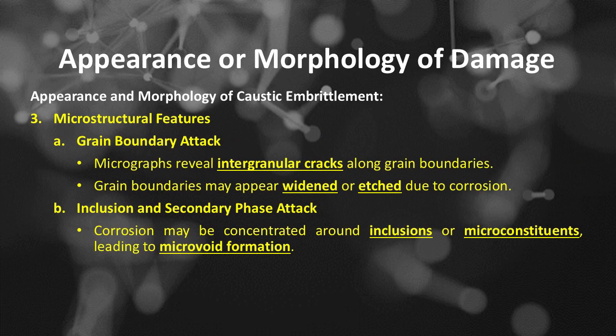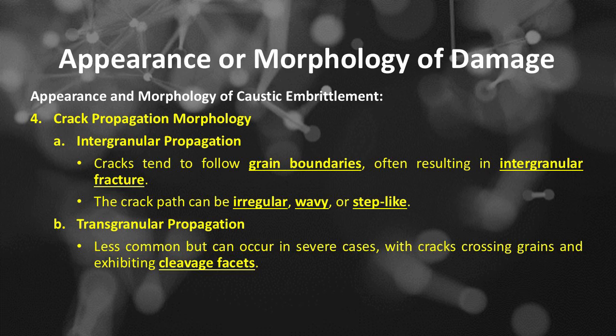Appearance and morphology of caustic embrittlement. Number 3 is microstructural features, which includes, number A, grain boundary attack. Micrographs reveal intergranular cracks along grain boundaries. Grain boundaries may appear widened or etched due to corrosion. Number B, inclusion and secondary phase attack. Corrosion may be concentrated around inclusions or microconstituents, leading to microvoid formation. Appearance and morphology of caustic embrittlement.